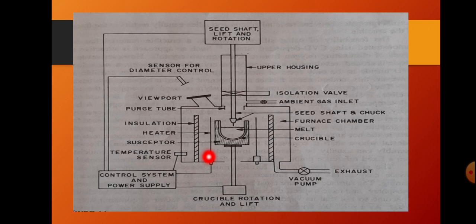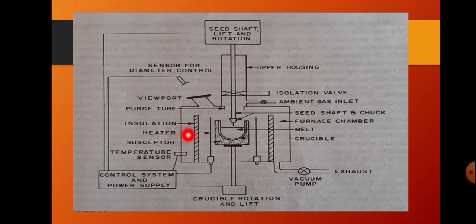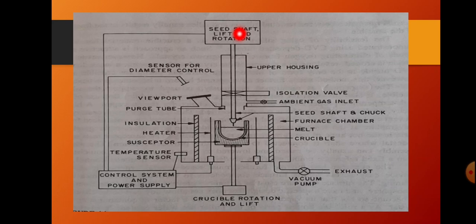There is a control system to control the temperature of the furnace. All components are insulated from the external chamber by insulation. The entire assembly is inside a chamber. The crystal pulling mechanism pulls the seed crystal upwards. The seed crystal rod is a highly purified silicon rod that is dipped into the molten silicon. When the seed crystal contacts the molten silicon, the molten silicon attaches to the seed crystal.